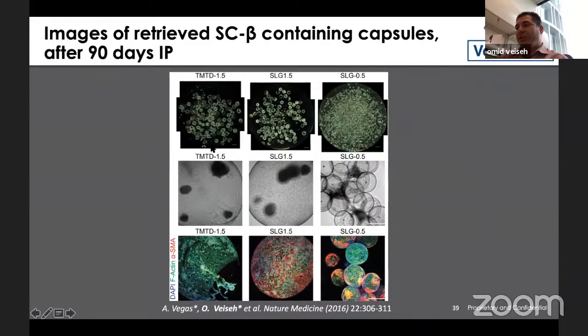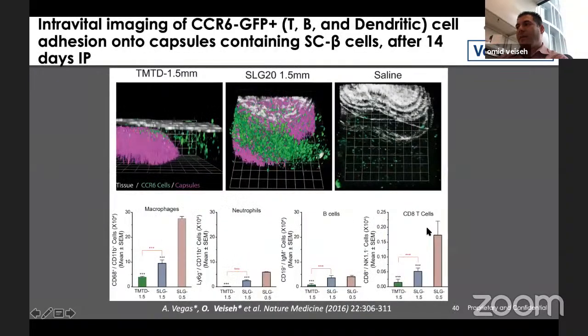With the modification, the myofibroblasts, which stain red, don't appear on these capsules. And when you have different sizes of capsules, small or large, without the modification, you can see that these myofibroblasts appear and the islet cells just start to die off.